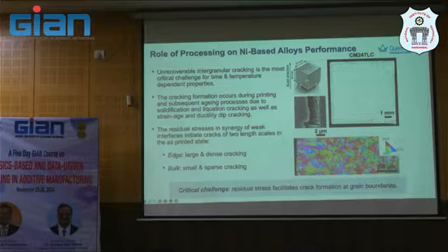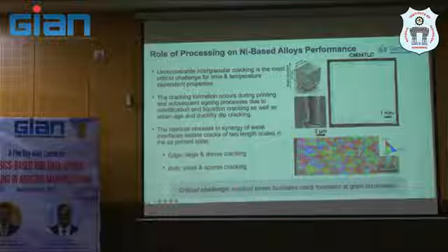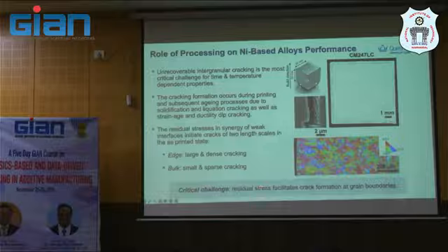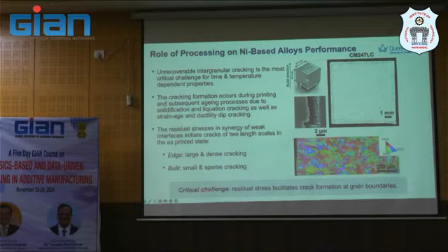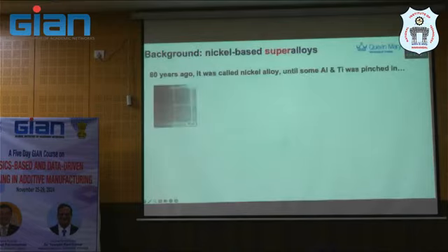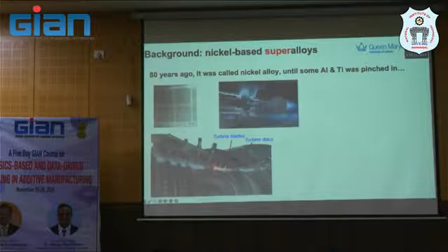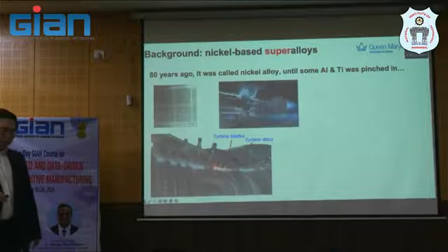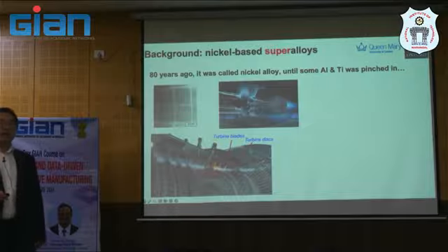So the critical challenge here, we believe the residual stress facilitates the crack formation at the grain boundary, and at the edge, also at the bulk of the material. And then, as you know, if we keep this in mind, in order to develop a new composition, we need to look back a little bit at what we need. And this composition is supposed to be used in high temperature applications. As we all know, this is for high temperature.